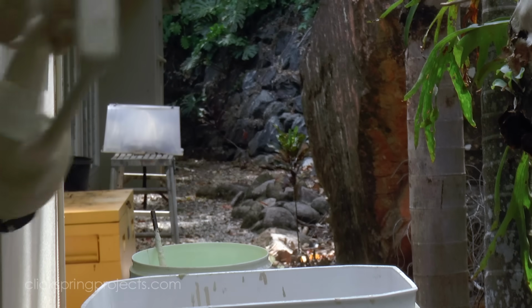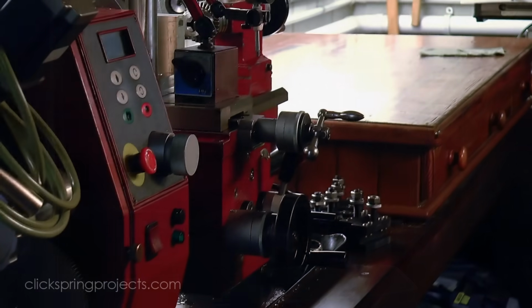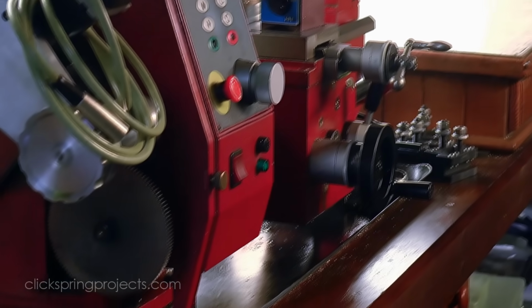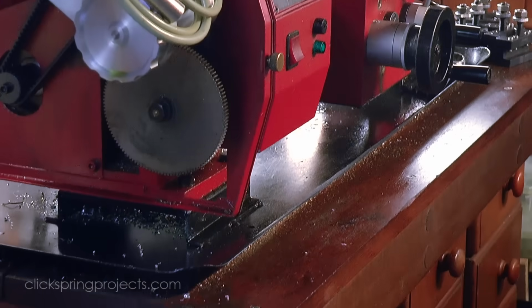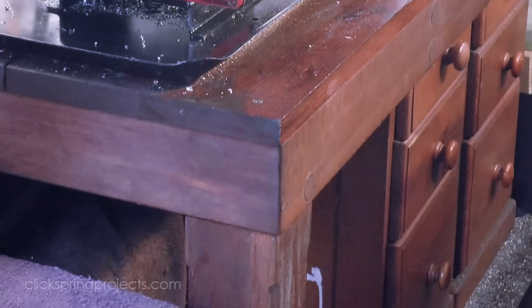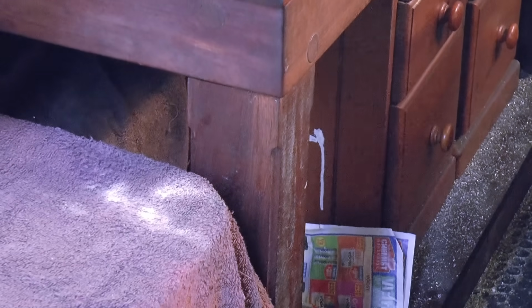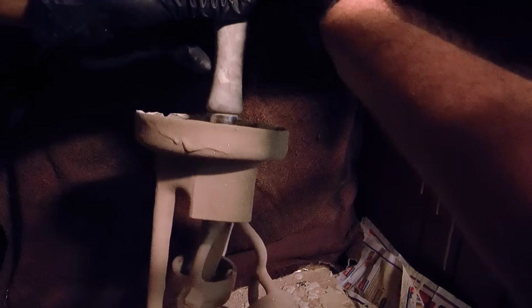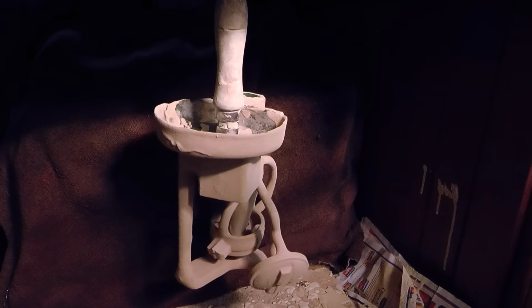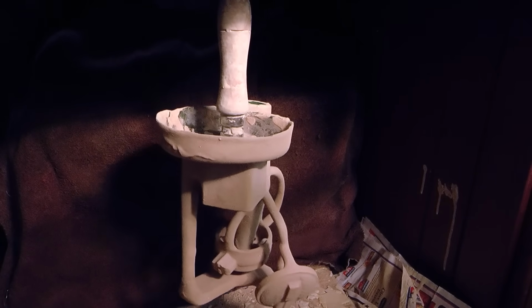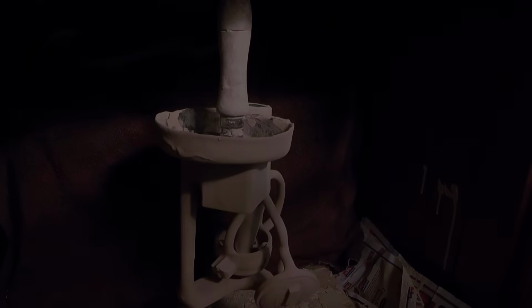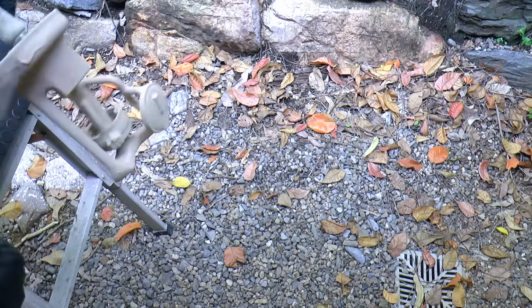Once covered in sand, the slurry will stop moving entirely, and the pattern can be put somewhere to dry. In this case, I have a small space underneath my bench, perfect for the job. I tend to leave the first coat to dry for 24 hours. Once the pattern is dry, the excess sand is removed and the process repeated.